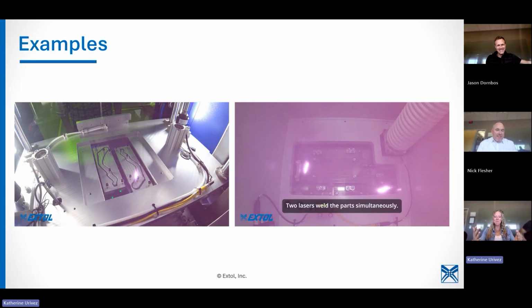But the point being, when you add the second laser source, although it was feasible with one, the cycle time went down to 14 seconds, from 40 to 14. And I'm kind of prematurely stealing Nick's thunder for a later slide, but this goes to the point that our goal is to help you configure the equipment so it fits your application. We may be able to do it with one, but to hit that cycle time, we would have had to have how many laser welders in this system? Or you put two sources in one laser welder, and then it goes faster.